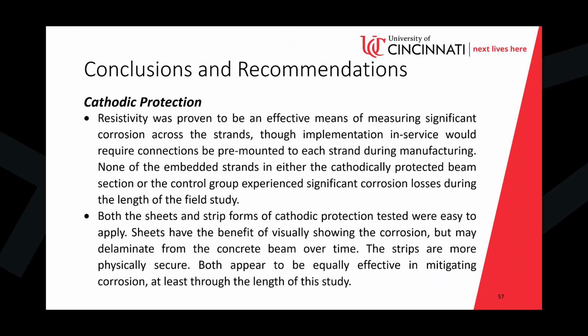And both the sheets and the strips were easy to apply. The sheets have the benefit of visually showing the corrosion, but may delaminate from the concrete beam over time. The strips are more physically secure, but both appeared to be equally effective at mitigating corrosion, at least throughout the length of the study. We actually extended the project a year, hoping to get a little more data from the corrosion protection, the cathodic protection work.